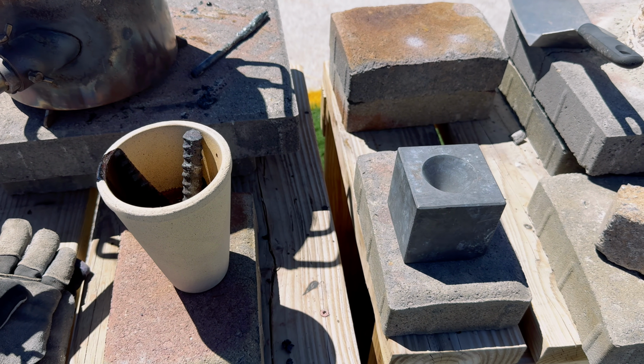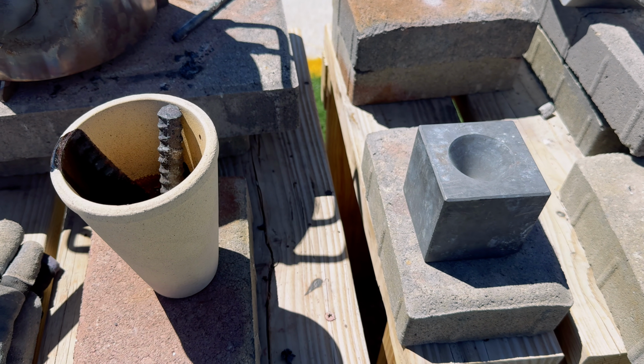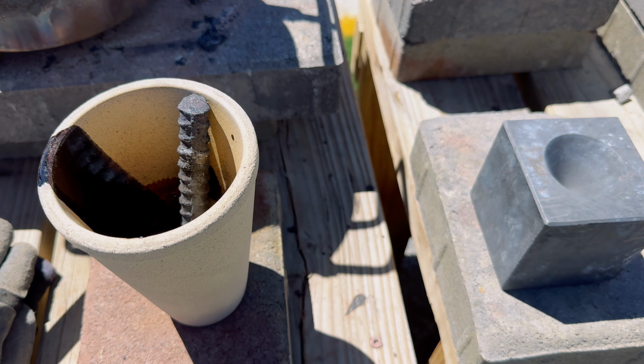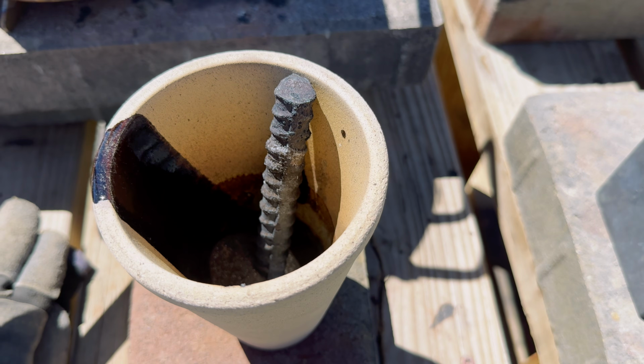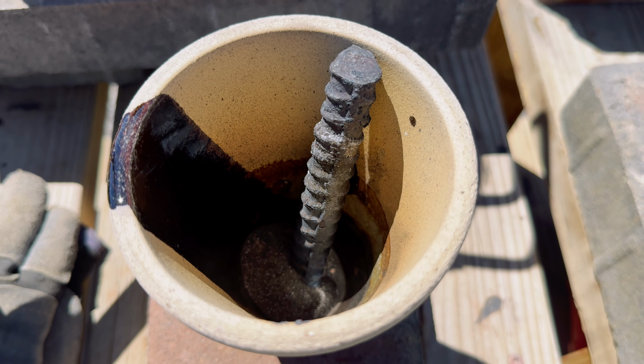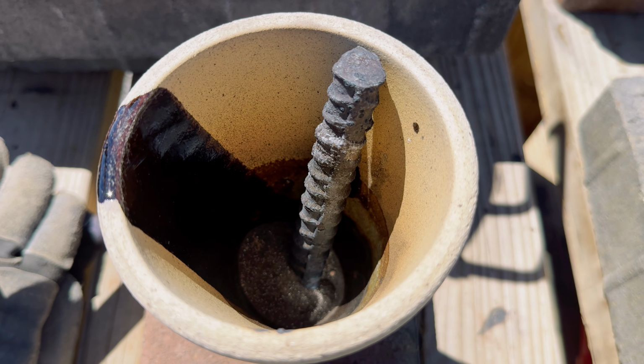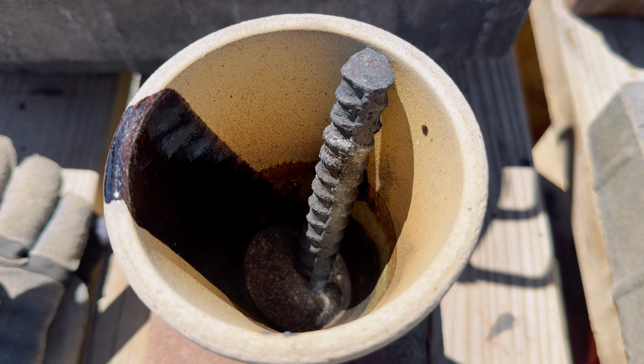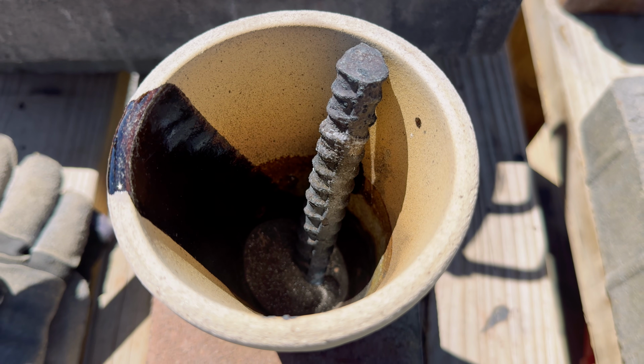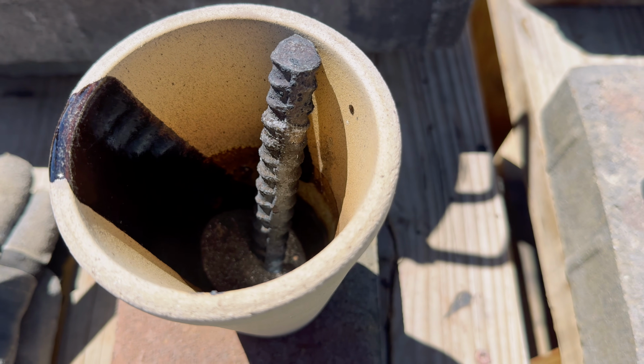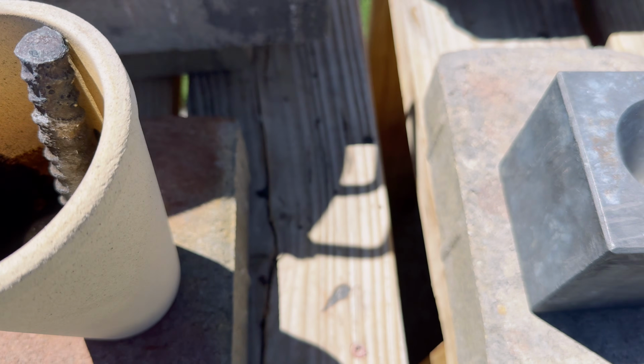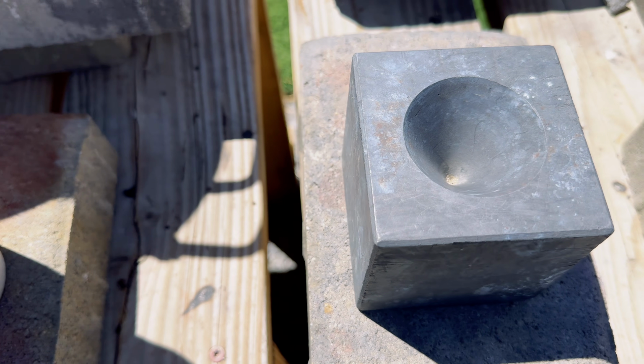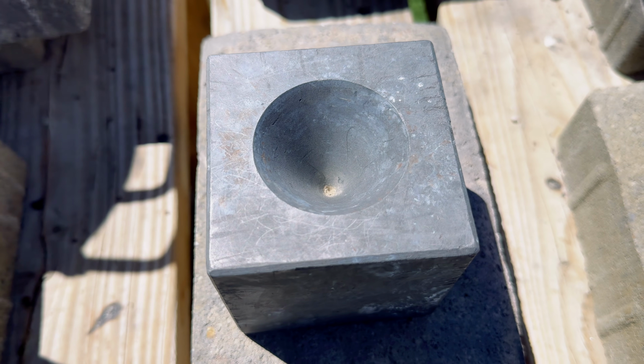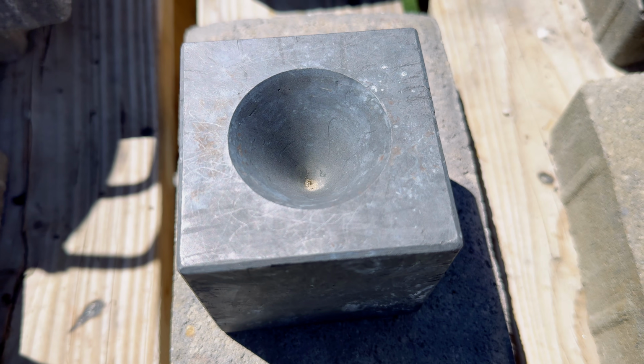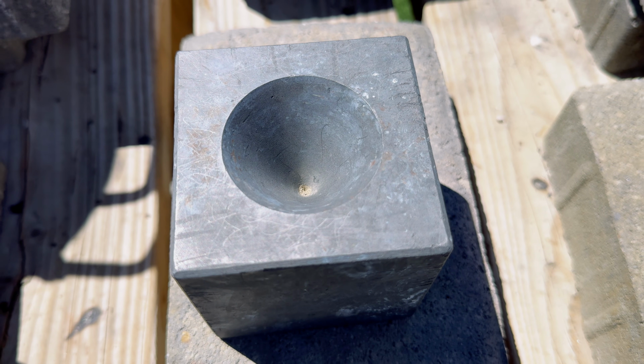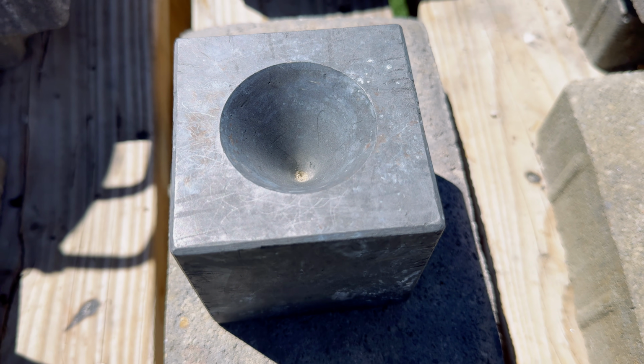We've taken our flux and our concentrate and poured it into this pre-borax crucible. The reason why I pre-borax the crucible is because we have very little material to work with and I needed to pour out of the crucible easily. I also have some rebar in our crucible to help collect the metal in our fire assay. Because the volume of our fire assay will be small, I will use our small cone mold for this pour.